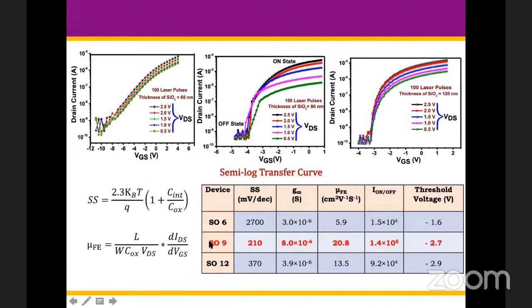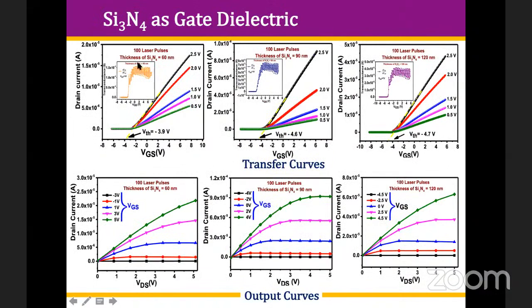So 90 nanometer thickness of silicon dioxide seems to be the optimum to make these devices. So then we tried, why can't we make it with silicon nitride instead of silicon dioxide? The same experiment was repeated with silicon nitride having 60 nanometer, 90 nanometer, 120 nanometer, and transfer characteristics and output